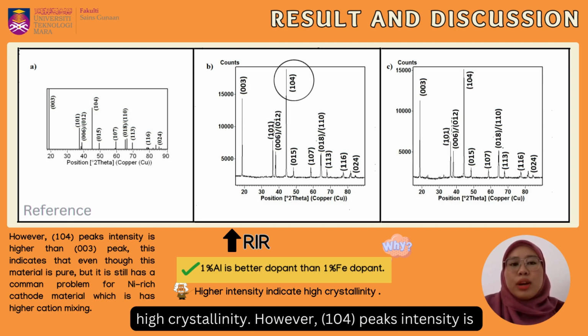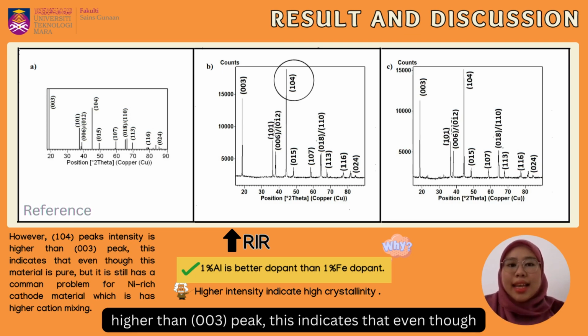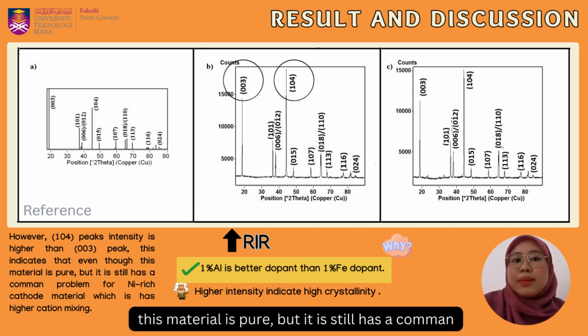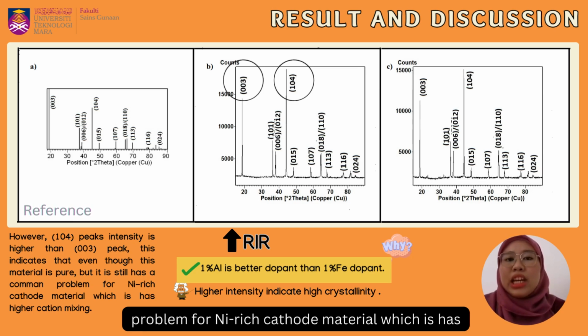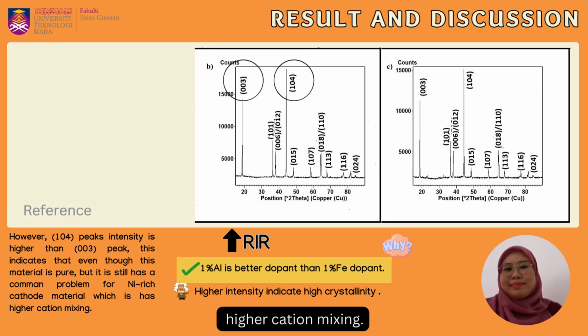However, the 104 peak intensity is higher than the 003 peak. This indicates that even though this material is pure, it still has a common problem in nickel-rich cathode material, which is higher cation mixing.